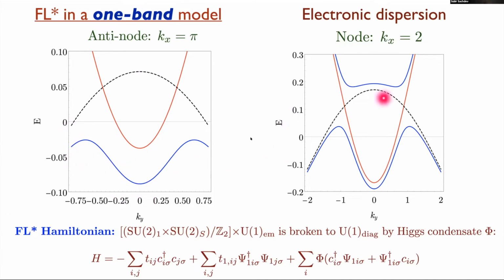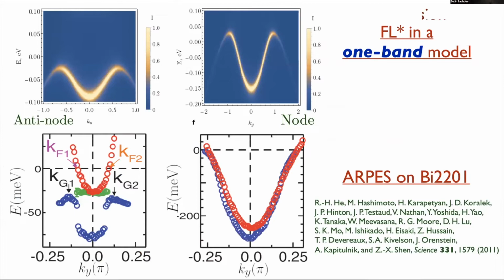On the other hand, if you look near the nodal region, the red line is what you get, which is actually very similar to what you would get on the overdoped side without any pseudogap opening up. All right, so here's a comparison between this data I showed you here. This is the blue line here, and the prediction on the antinodal side, and this is the nodal dispersion. And also, this doesn't vary very much with doping at all, whereas this, as in other models, that's not the case. Okay, so it seems like we get all the basic features.